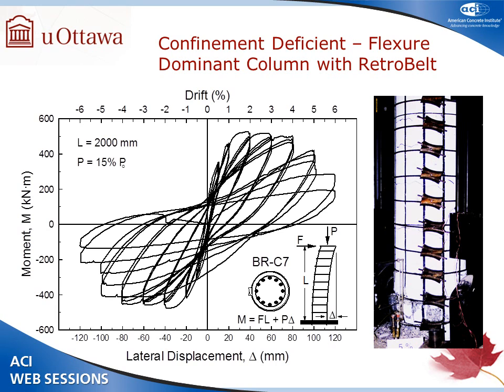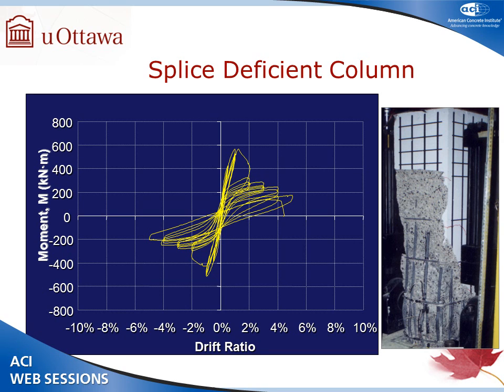And here's a companion circular column. Again, we were able to go up to 4% without any problem, and transverse prestressing seemed to work. Where it was most effective, whereas some of the other techniques, especially FRP jacketing, does not work, is square and rectangular columns with splice deficiencies. In fact, in the Canadian standard for FRP, we do not allow use of FRP for strengthening against splice deficiency. If it is square or rectangular, for circular it works, but otherwise, because of the passive pressure, it does not provide sufficient clamping force, whereas transverse prestressing does that.